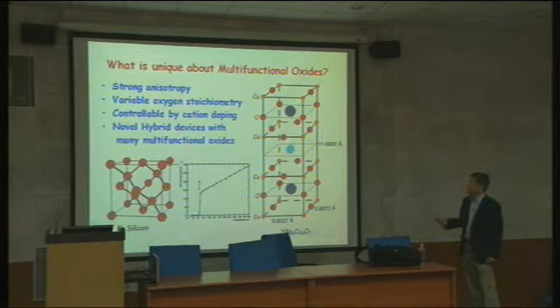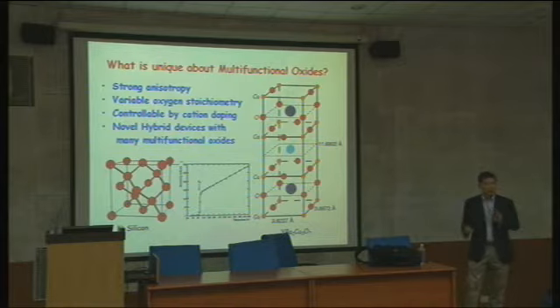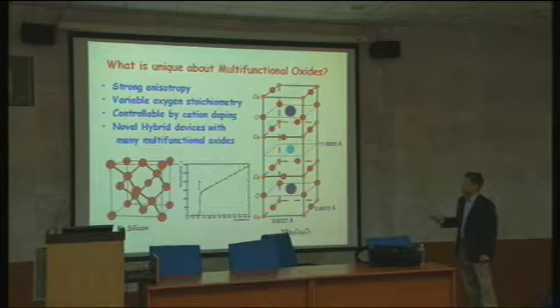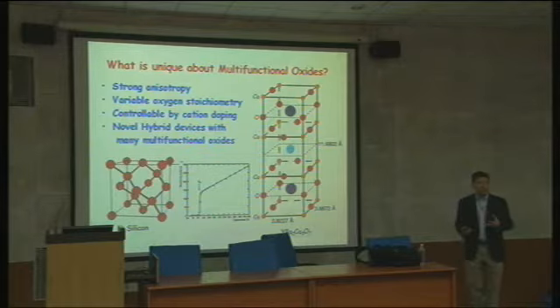And oxygen, as I said, can go in and out, so oxygen stoichiometry is very important in this system as well. Also cation doping, especially, produces a metal-insulator transition. For example, in the first superconductor discovered, the lanthanum barium copper oxide system, without any doping of the barium, it is itself an antiferromagnetic insulator. But when you add the dopant, it becomes metallic and superconducting. So cation doping is also very important. That's why work in the complex oxide system is not just physics work only. It involves physics, solid state chemistry, materials synthesis, and all different types of fields.